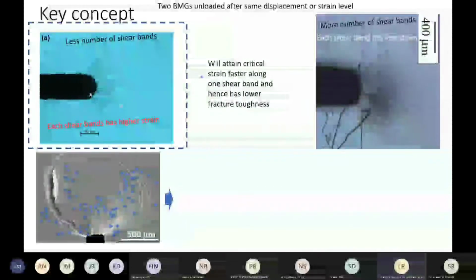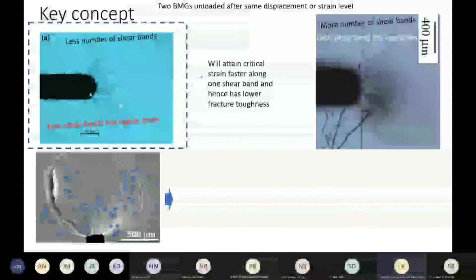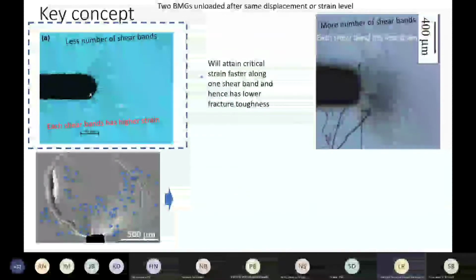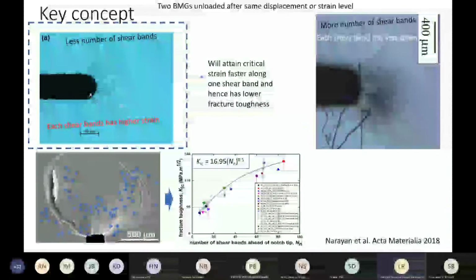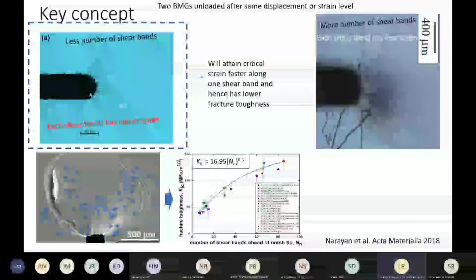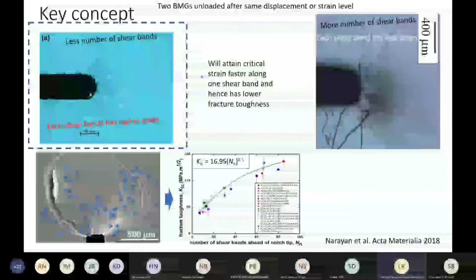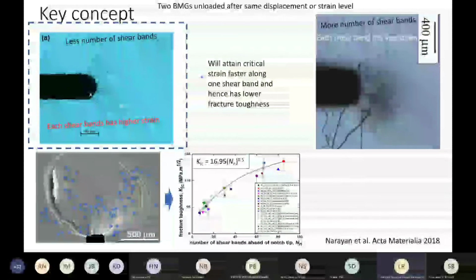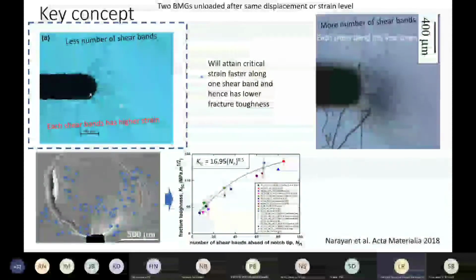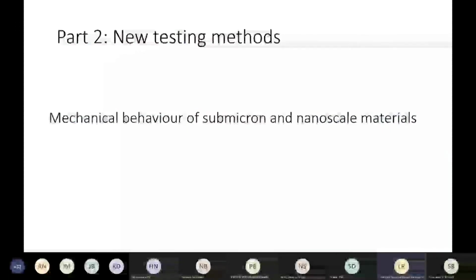So using that idea, what I did, in fact, was to collect the shear band envelope on several metallic glasses. We examined about 22 systems, and then what we did was we found the number of shear bands actually correlates with the fracture toughness of the material. So once you're able to measure the number of shear bands in front of the notch tip, you can actually calculate or estimate the fracture toughness of a material. And this was one of the ideas with which a materials engineer can understand the concept of mechanics, or even apply empirical theory to know what the mechanical property of a material is. So this is very unique to a metallic glass system and cannot be done for other materials.